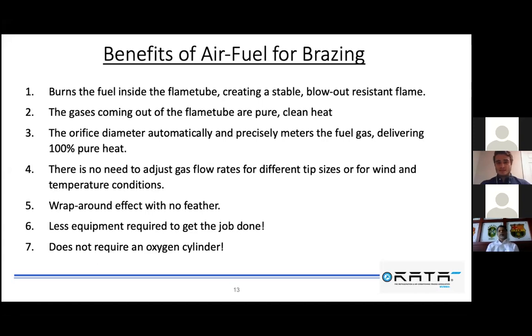It is less equipment required. You do not need to adjust the flame, the flows of the flame on the torch. So when you have an oxyfuel torch, you have to adjust the pressure on the regulators according to the tip that you are using, and also the valves on the torches to adjust the flow and everything according to the tip that you are using. So you have a very unique measure basically for each tip that you are using in the job that you are doing.